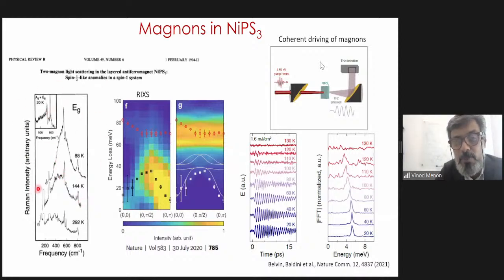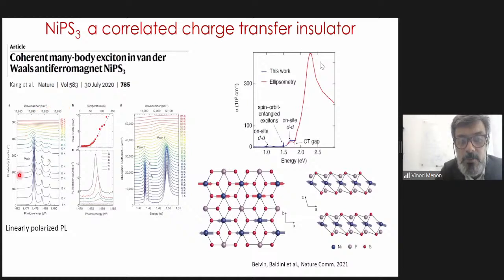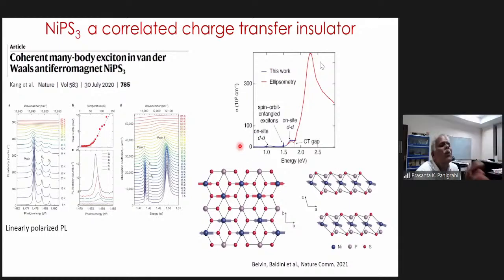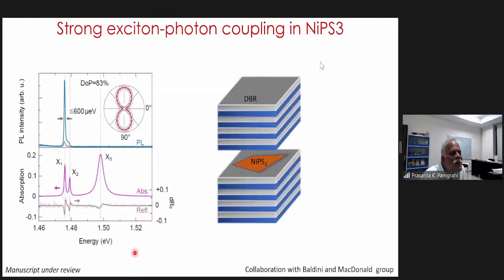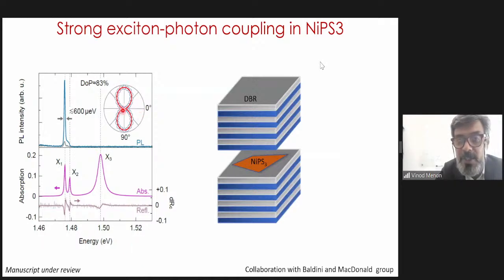But the reason I wanted to point out was that these materials were studied before and people had seen the Magnons. But what for some reason everyone had missed was the presence of these excitons inside this material, and the fact that these excitations seem to be correlated with the Magnons because the polarization of the light emission is always perpendicular to the spin chain. Oh, okay. Yeah. So in fact, you will see here in our results, for example, they're beautifully linearly polarized. And this linear polarization is always perpendicular to the spin chains inside the system. Thank you. Yeah.